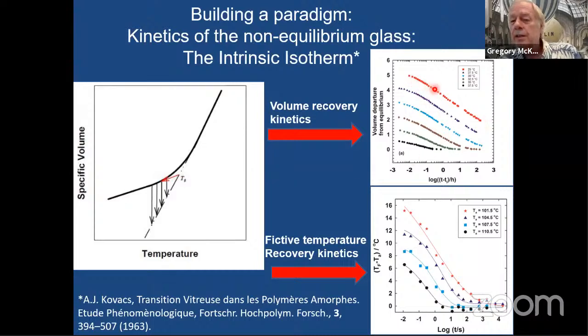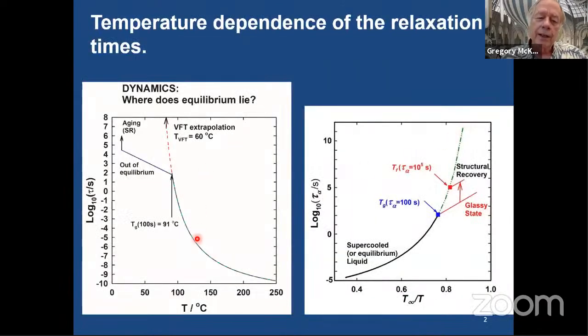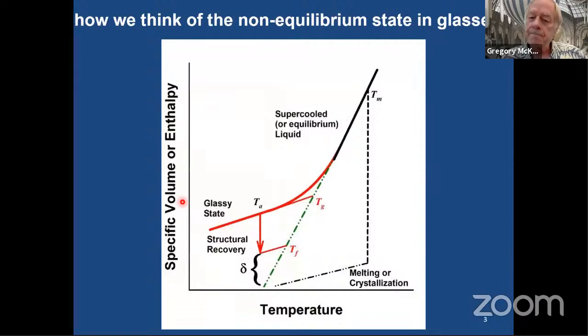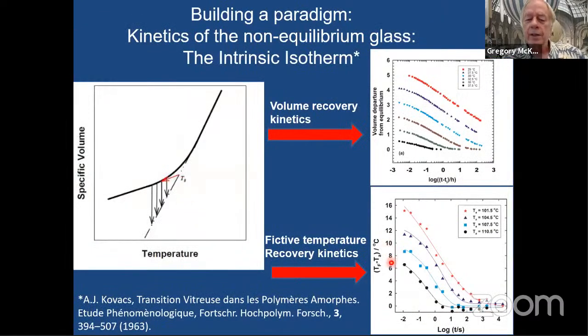So you can see that these things are fanning out, and this is what you sort of expect as you get longer and longer times as the temperature comes down. Whether or not those times are as long as these times is also related to the question of whether or not we have this divergence. The other thing that's important is that this data is from Simon and her co-workers using enthalpy recovery, and she measured the fictive temperature, and the fictive temperature does much the same thing as what the volume departure from equilibrium does.